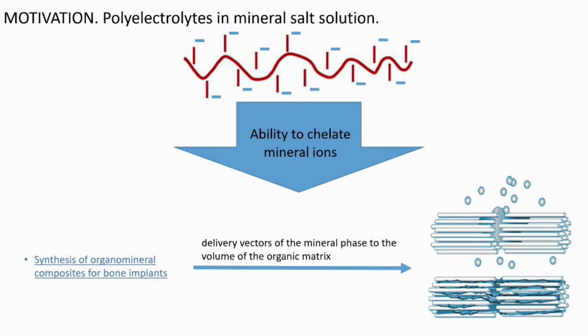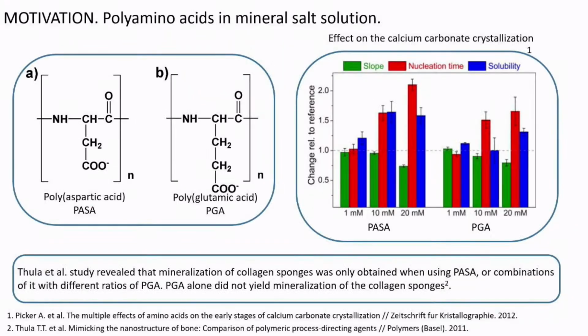for such mineralization, and they saw that without polyelectrolytes, the collagen matrix mineralized only on the surface, but if we use polyelectrolytes, mineralization occurs in the volume of the organic matrix. So we investigated two polyelectrolytes. They are polyamino acids: polyaspartic acid and polyglutamic acid.